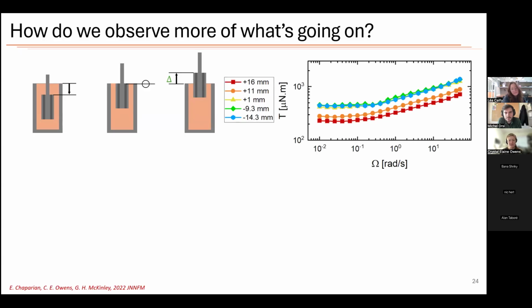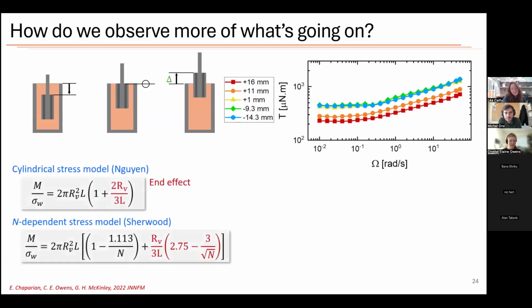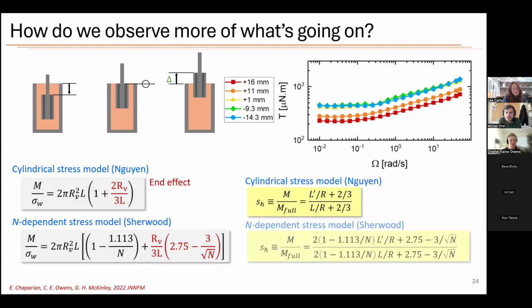Here, this is in machine units. This is in rotation rate and torque rather than stress and shear rate, because we're still figuring out what's going on. And we have the equations that we had before for the torque as a function of everything else. And from these equations, we could work out likely conversion factors if we wanted to understand the material properties of a material that we're measuring with the vane not completely submerged. So we made two conversion factors.